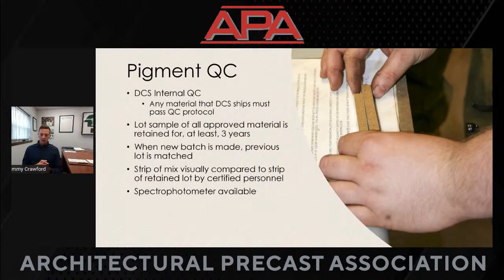The short answer, Mark, I'll touch on this question now. Mark Fairman asks, does mixing time change the color of the mix for powder or liquid? The short answer is no. As long as you mix it sufficiently, which does depend a little bit on your operation and what kind of mixer you're using, I would say 60 to 90 seconds should be sufficient. As long as you're mixing it sufficiently, the end resulting color should be the same. If you're under mixing, then that can be a problem, regardless of if it's powder or liquid. Hope that answered your question.